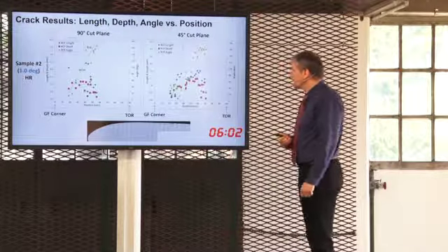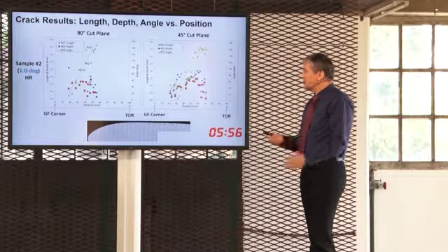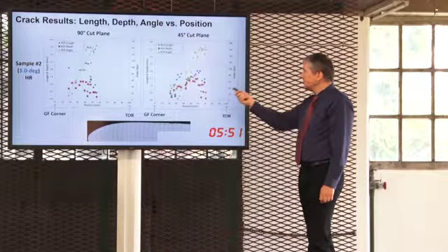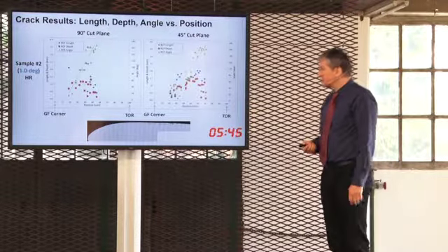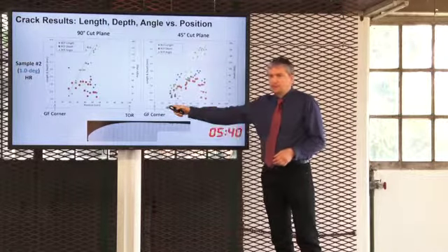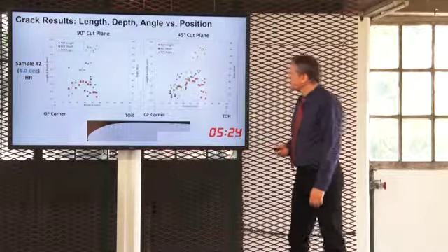When you start doing this for higher-angle curvatures like a 1 degree, you see now that the distribution shifts more to the center. Comparing the 90 plane cut and the 45 plane cut, the angle looks fairly similar. This builds confidence, because usually when people think of RCF, they see the 2-dimensional slice and look at this crack, but the crack plane is 3-dimensional. It's like a leaf going into the rail. As you do multiple slices, you start building a better understanding of what this looks like subsurface, right? And the density of cracks is better here.